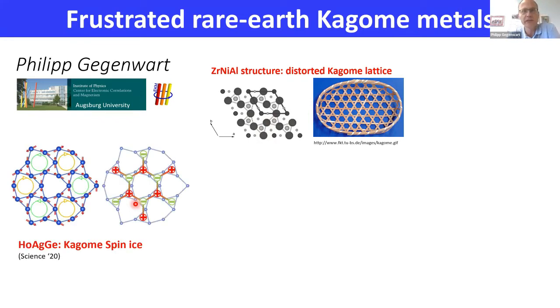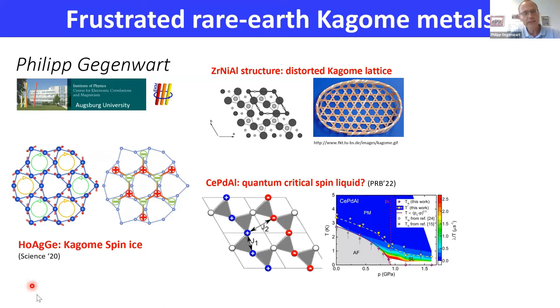The first example I will mention is holmium silver germanium, where we recently found the first crystalline realization of a two-dimensional spin ice state. More recently, we see very interesting coupling to the conduction electrons, which gives rise to interesting Hall and magnetoresistance behaviors. While here we have a negligible Kondo effect, there is also, of course, the question: what happens if you get to heavy fermion metals or Kondo lattices, where the f electrons are placed on this Kagome lattice? And here we also have some interesting new developments.